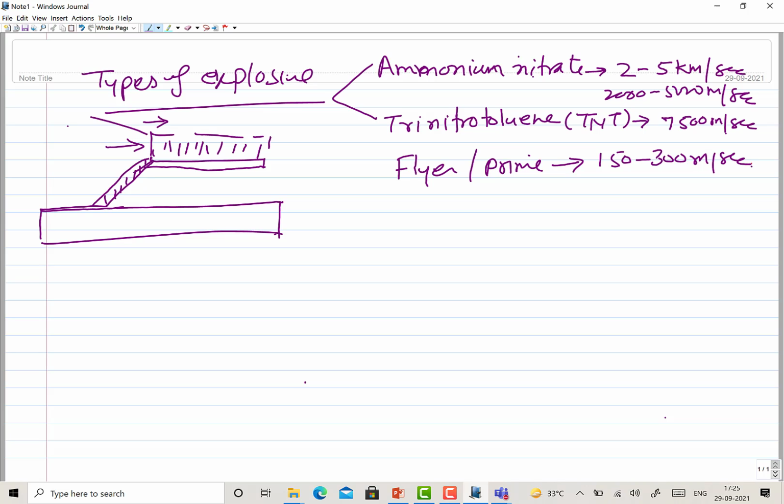That is the kind of speed which is realized, and when it impacts at the interface, it results in pressure at the time of impact. The impact pressure is extremely high, like 10 to the power 5 MPa, but it acts on a very thin layer at the interface,